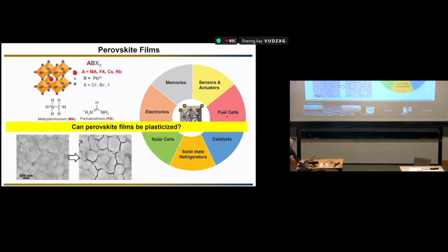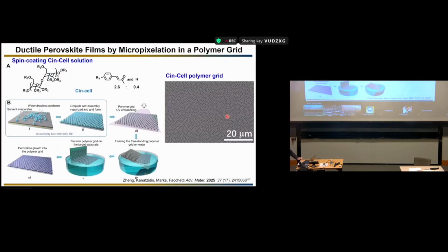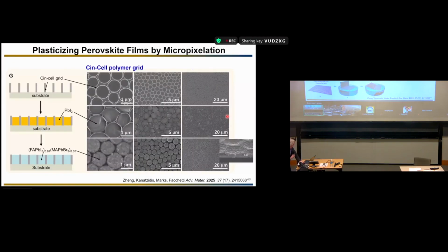The way we started doing it is by learning from the work we've done on an electrochemical transistor. What we did here, we took a plastic polymer. This is not a semiconducting polymer, this is just a plastic polymer. This polymer has been spin-coated at a very high relative humidity. When you do that, you create this honeycomb, these holes in the polymer film. Then what we did is, inside these holes, this grid is basically the holes cut from the side. These are SEM images of the polymer.